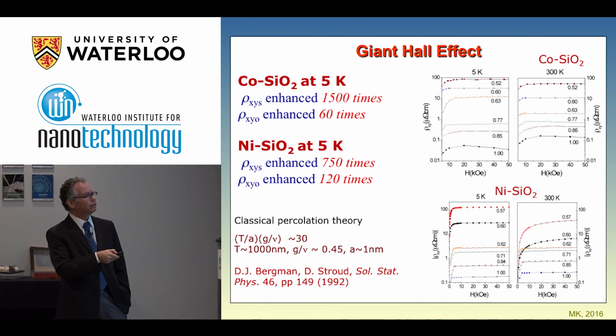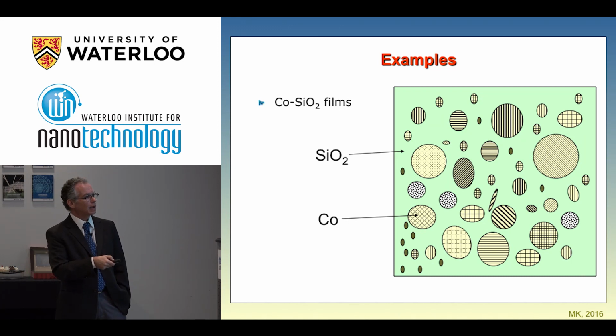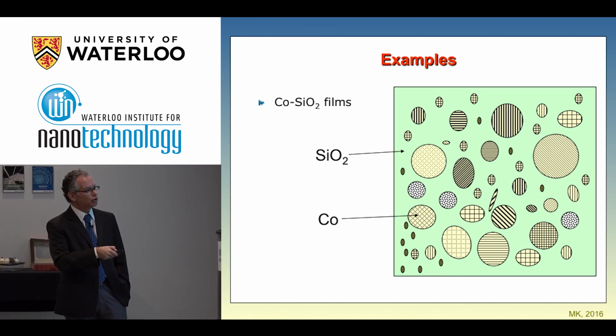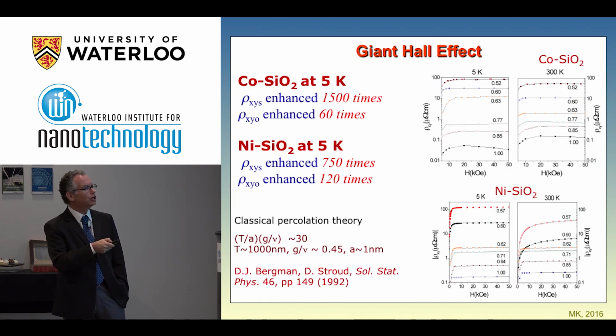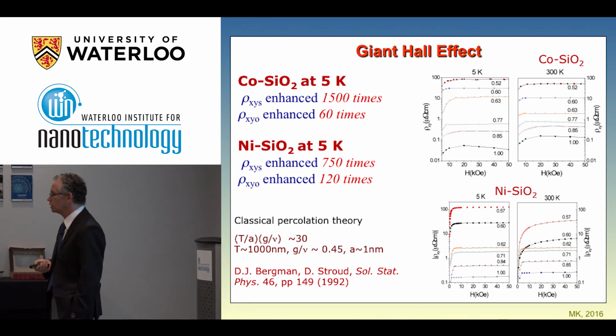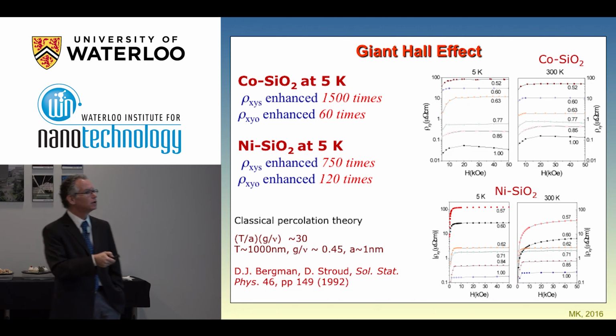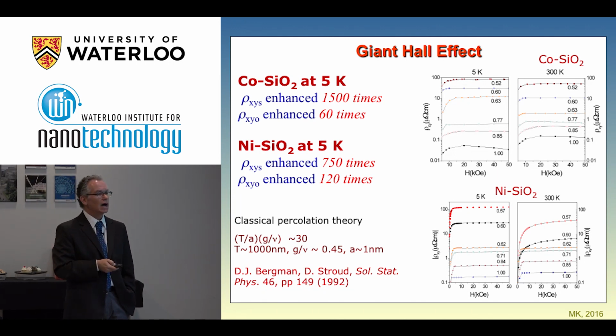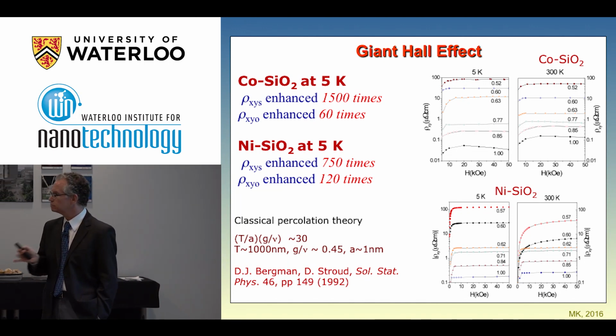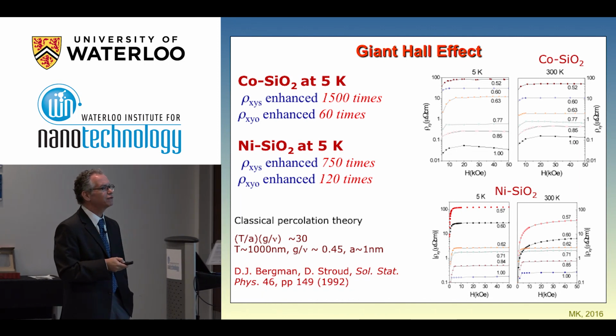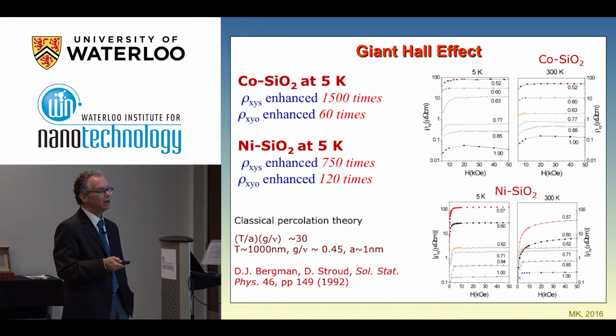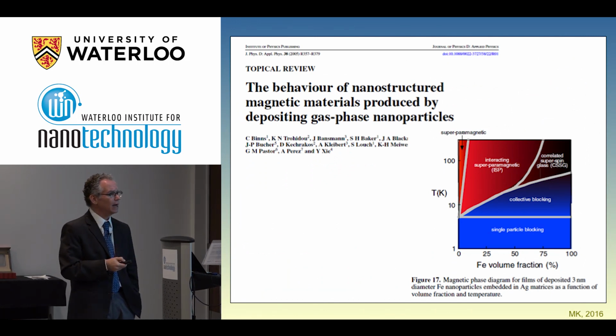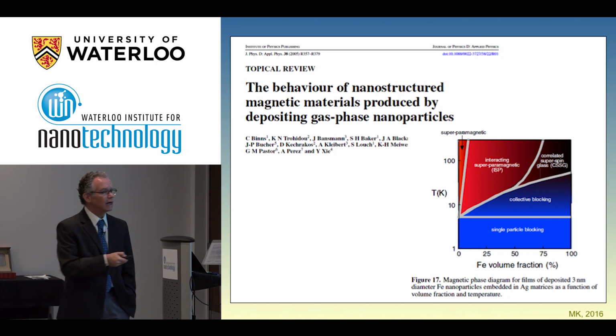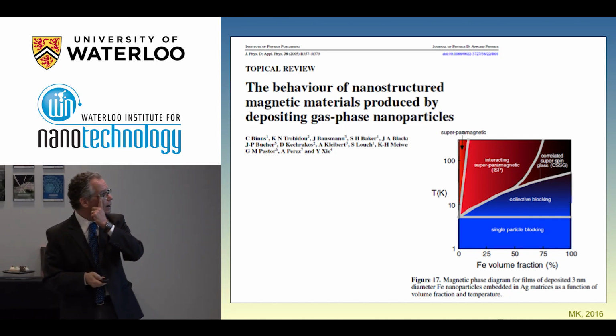Just in the metal transition, whenever you start populating the cobalt concentration here, and you go through this transition from insulating to conducting material, you have a huge Hall effect, which is called the giant Hall effect, just happening in the metal insulator transition whenever you change the composition. And up to now, there is no theory about this effect yet. So this is something that is completely open in the community, in the magnetic data. And you can have a very interesting phenomenon here related to interactions.